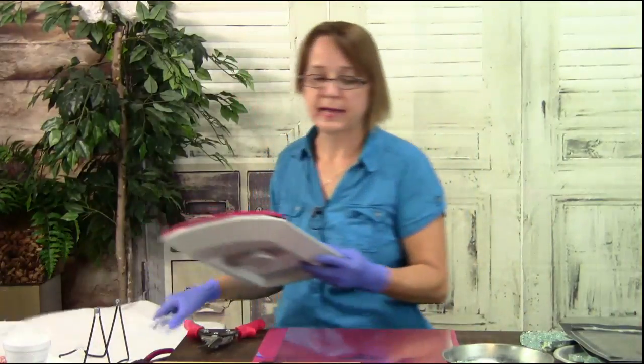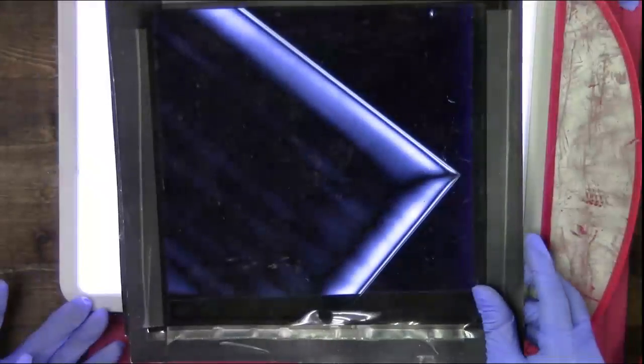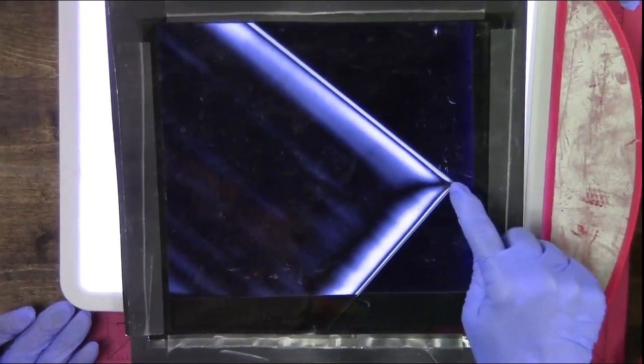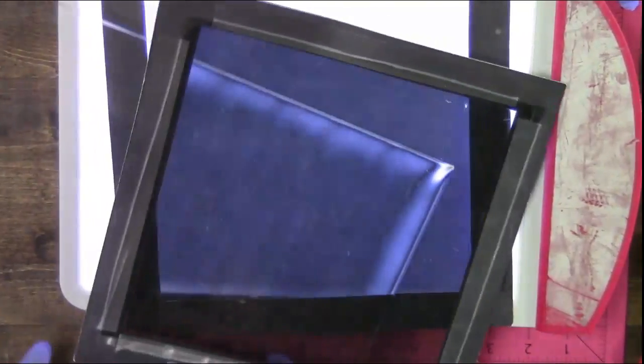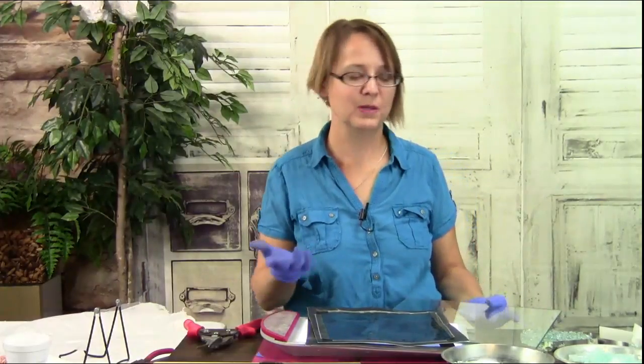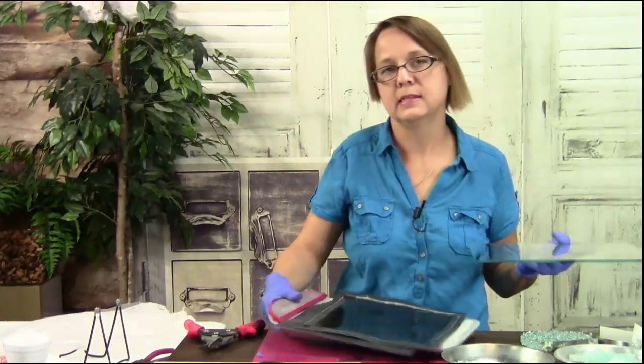But sometimes tempered glass doesn't have a marking on it. So how do you tell if it's actually tempered? We have polarized film. Yes, you can look at it with your polarized film. Oh, wow. Isn't that cool? This halo that you're seeing right here is very distinct, particularly on the corners, and particularly on camera, too. So you should have no trouble figuring out if it's tempered. If you are in the thrift store and you're not sure if something is tempered, I have little squares of polarized film, and I put them on top of my cell phone as a light box. It works great. It's very discreet. People look at you like you're a weirdo, but it is pretty awesome. So that's two ways you can tell it's tempered: either by the tattoo on the glass, or by looking at it with polarized film and seeing the stress inside.